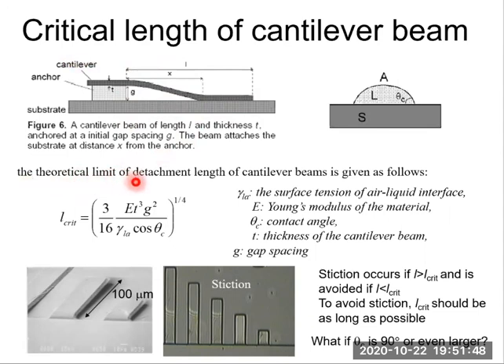The theoretical limit of detachment length, namely the critical length of cantilever beam, is given by this equation. L critical is equal to the fourth root of 3 over 16 times E, where E is the Young's modulus of the cantilever material. For example, for polysilicon, E is 160 gigapascal. T is the thickness of the cantilever beam. And G is the gap spacing, the gap between the cantilever and the substrate. Questions?